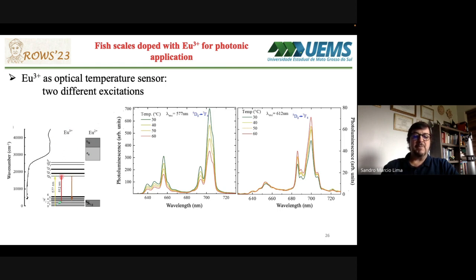But we performed the experiment here, exciting at 577 nanometers to promote the electrons from the 7F0 level to the 5D0 state. And we observed the photoluminescence in the red region that is shown here. We are observing the transition here from the 5D0 to 7F4 state. The samples were heated from 30 to 60 Celsius degrees.